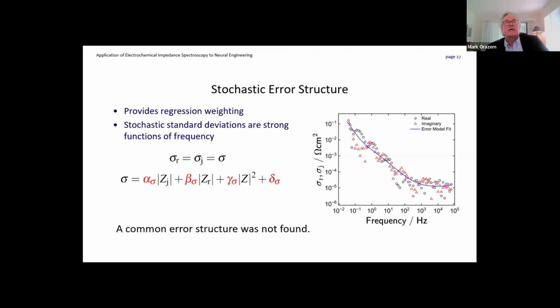But basically, what we're saying is that as we change the potential, I think that the equilibrium concentration of the different redox states for the iridium changes. And that gives rise to different error structures. So we had to use a different error structure for every potential.